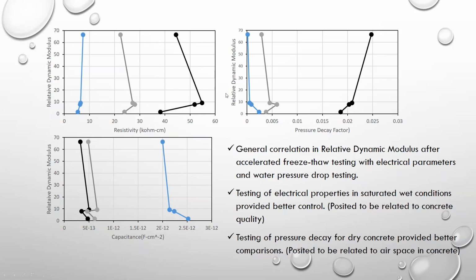On the other hand, we also correlate our frost freeze thaw attack, the relative dynamic modulus, to that pressure decay factor that we're talking about. And first condition, we can pay attention more to the dry conditions, where the samples were in dry conditions. Again, to try to control the initial setup during testing. And we can see that we have better frost freeze thaw resilience for samples when we have a larger pressure decay factor. And this we're ascribing to those samples that have a larger air content.